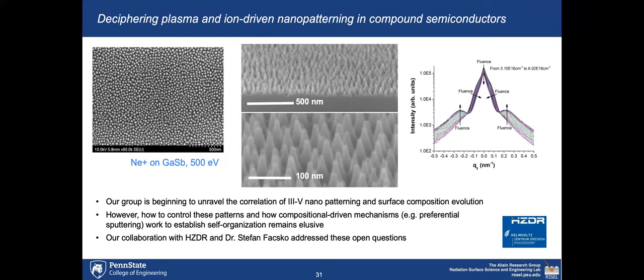Do you see much effect if you change the substrate temperature, or is the energy of the ions so much more important that it doesn't matter much? Yeah, that's a great question too. And I didn't clarify, so all these samples were kept at room temperature. The ion beam itself, because of the low flux, only raises the surface about 50 degrees Celsius, sometimes 100. We control that by actively cooling the sample.